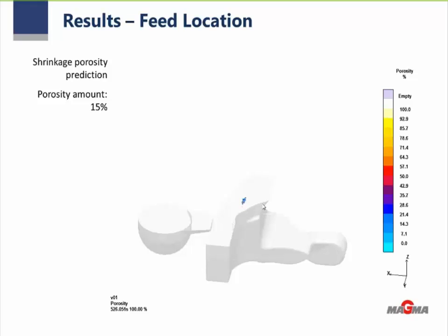So this porosity is not good for our model, but it would be worse if you saw this porosity in the same place as the critical stress for static analysis, for example, or fatigue. But here they are far from each other.